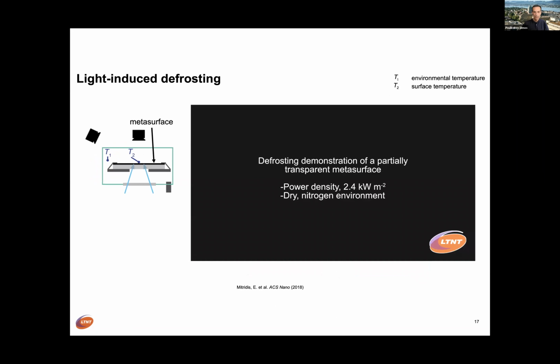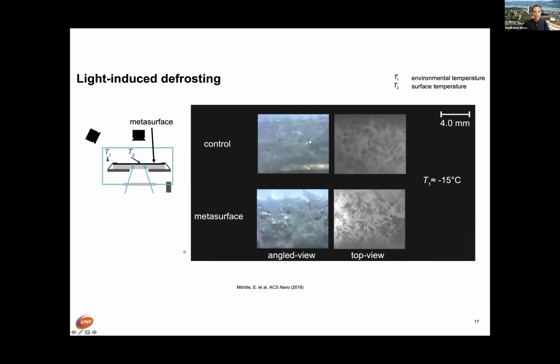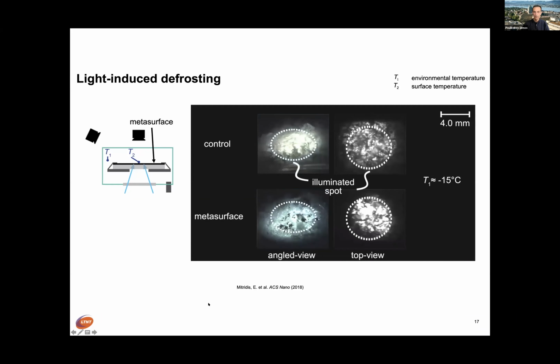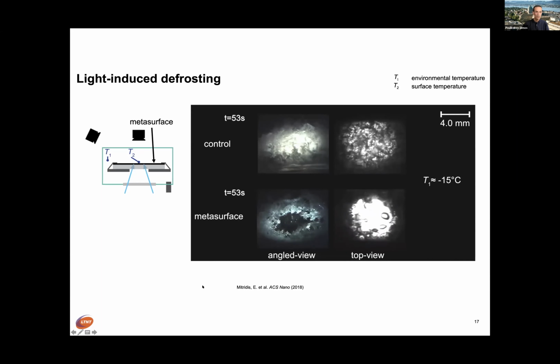And I will show you only one slide, which is a film. So we did the surface, it's a photothermal metasurface. And then effectively we test it. And as you see, the control surface is on top with frost on top of it, and the metasurface at the bottom. We turn on the light, and you see the tremendous difference between the two surfaces, of course. After about 30-40 seconds, we have complete melting of ice on one side, and on the other side, actually, we go to several hundreds of seconds, 400 something, I think, and nothing happens. So it has a tremendous effect, all right?